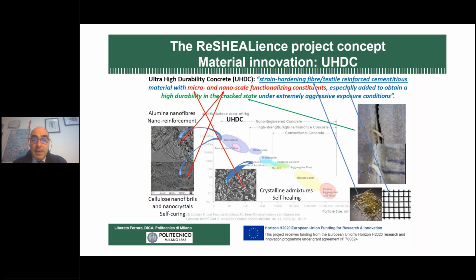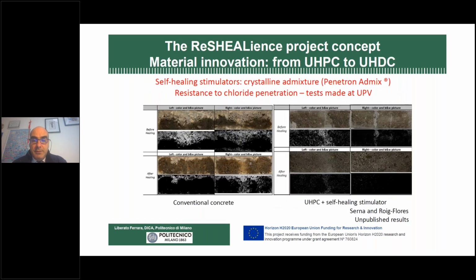We started with the technology of ultra high performance concrete, ultra high performance fiber reinforced concrete, and we engineered its composition using micro constituents and nanoscale constituents to promote self-healing, to promote self-curing, to have a very extreme, I would say, control of the crack width, because we were able to control the width of our cracks in the range of a few tenths of microns. We use alumina nanofibers, cellulose nanomaterials, and crystalline admixtures for self-healing.